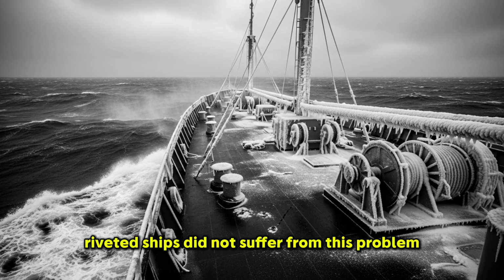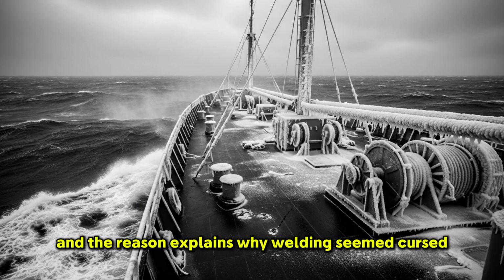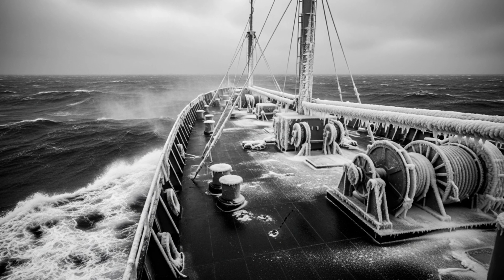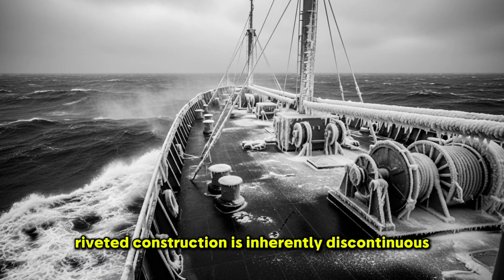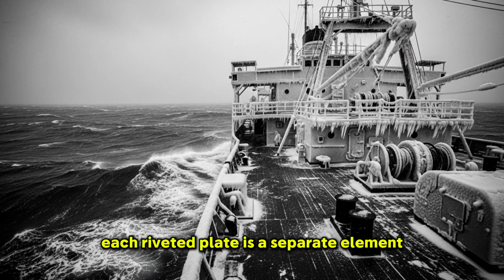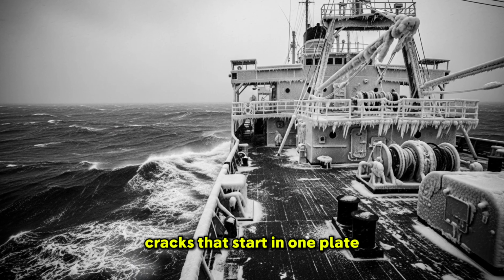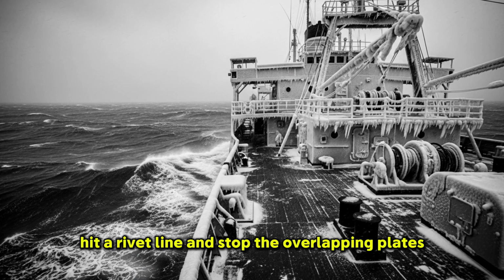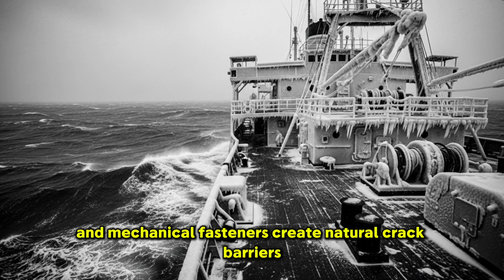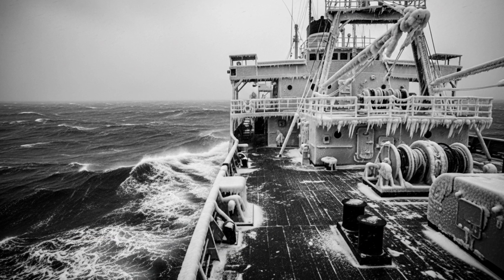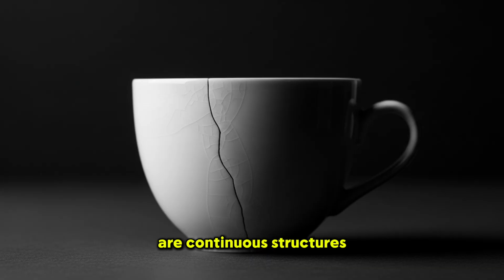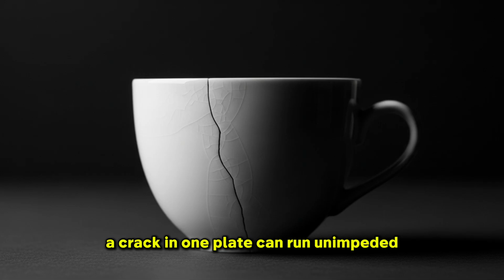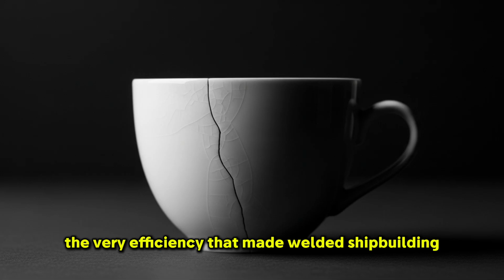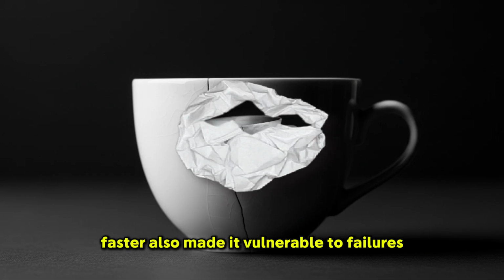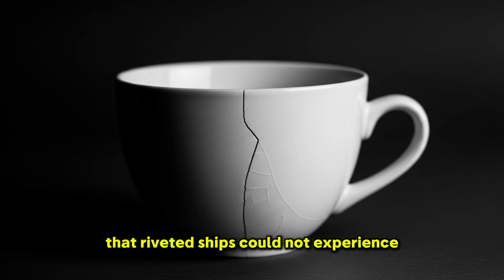Traditional riveted ships did not suffer from this problem, and the reason explains why welding seemed cursed. Riveted construction is inherently discontinuous. Each riveted plate is a separate element. Cracks that start in one plate hit a rivet line and stop. The overlapping plates and mechanical fasteners create natural crack barriers. Welded ships, however, are continuous structures. A crack in one plate can run unimpeded across hundreds of feet of fused seams. The very efficiency that made welded shipbuilding faster also made it vulnerable to failures that riveted ships could not experience.